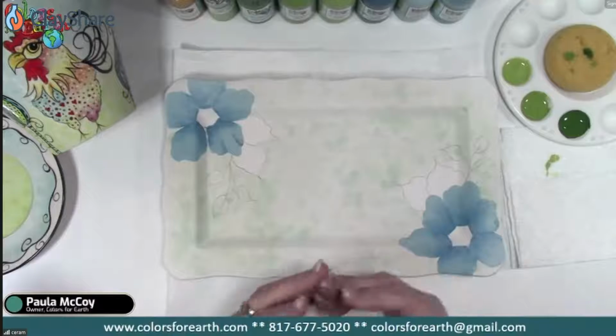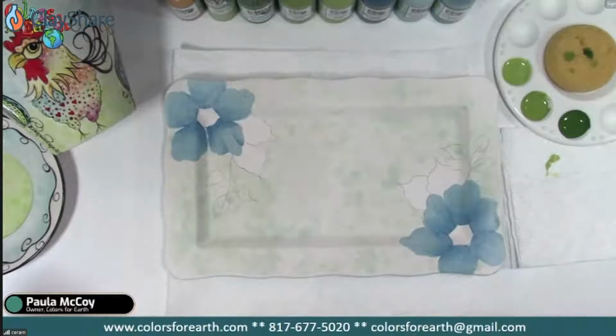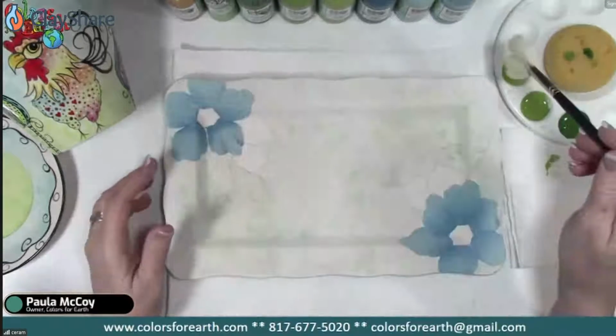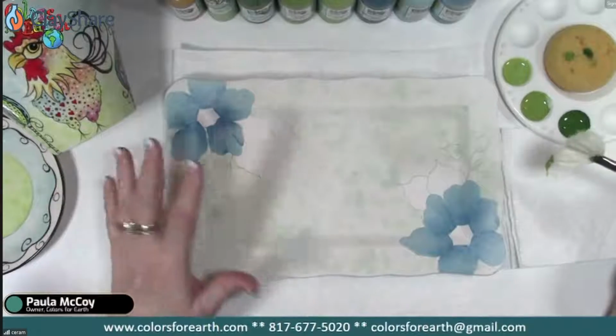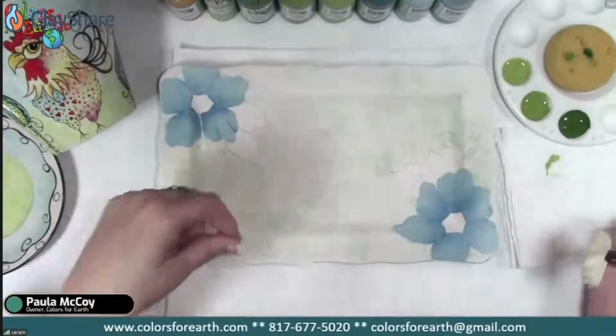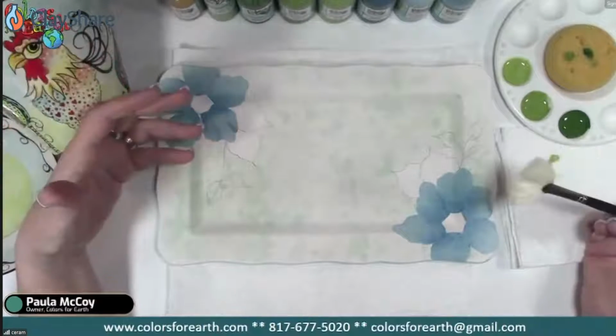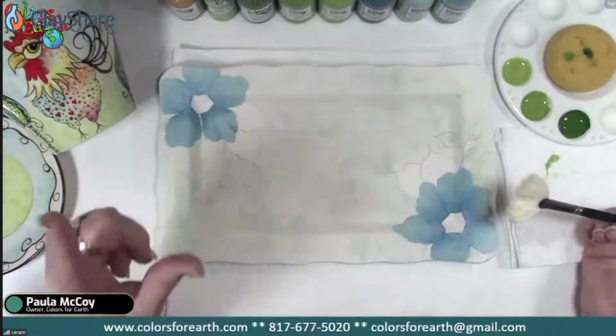And I know there's a myth out there that the longer you let it dry, then your colors won't smear. I, for 20 plus years, have been doing this method. So if I were going to glaze this piece, I'd grab my soft fan brush and I'd get into my glaze and start glazing it after I misted it. Okay. The reason why is the longer this sits on the shelf and it dries, there is a product dust that is on the top surface. And especially, I used to have a lot of the contemporary PYOPs that would be dipping their pieces and they have pinholes. Well, if you mist your piece before you dip, you can try to avoid that.